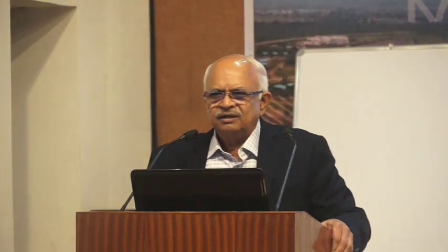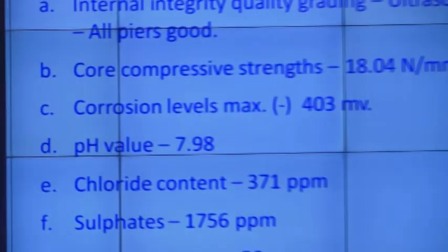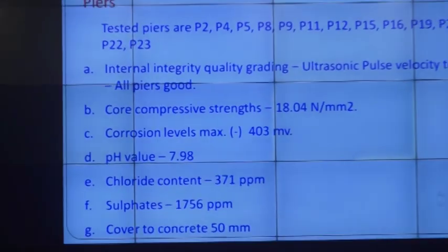That's exactly the reason yesterday I told you, when you want to rehabilitate a structure, please take out a core, you don't do anything first. Whether it is fit enough to do the rehabilitation, investigation also you can make out. You just take out a core, cut it, test it for pH value, if it is quite less, no need to do anything further. No need to put your stethoscope there. You can simply say put a new estimate, replace that. Only superstructure.